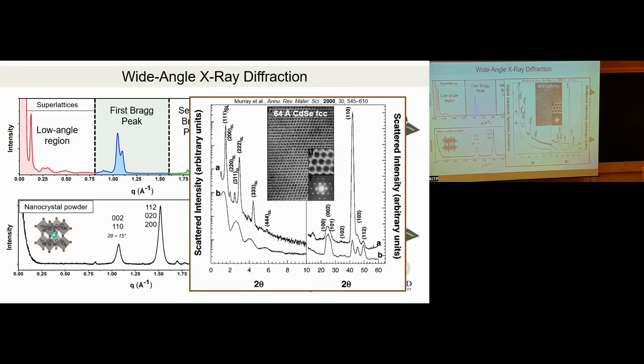Again, to give a reference point, if one looks at the classical works from the Bawendi group in the late 90s, so FCC cadmium selenide superlattices, here's a low angle X-ray diffraction, but then at the wide angle X-ray diffraction, what they saw in these materials is basically just an effect of preferred orientation, but no additional modulation.